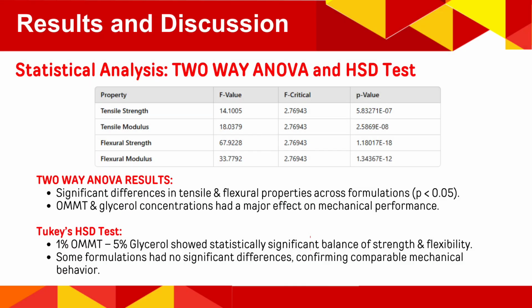We conducted a two-way ANOVA to assess the significance of the nanoclay and glycerol concentrations on the mechanical properties. The results showed significant differences across formulations. This confirms that both additives influence the material's performance. The HSD test further identified which formulations differed significantly. This reinforces our selection of the 1% nanoclay and 5% glycerol as the best candidate.